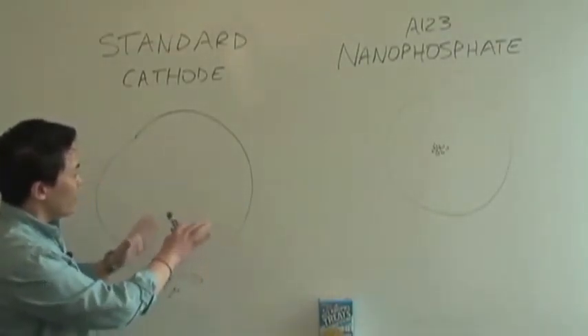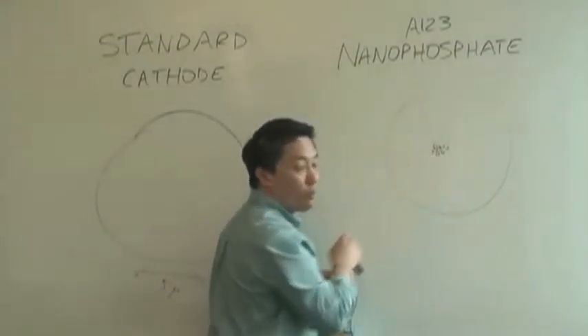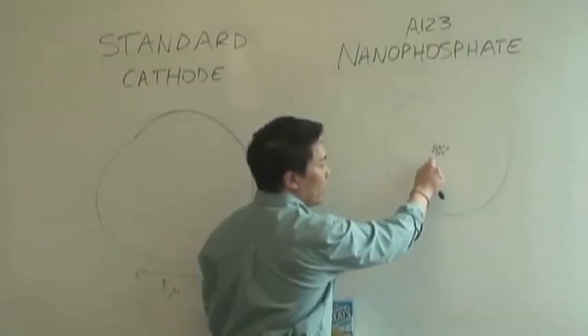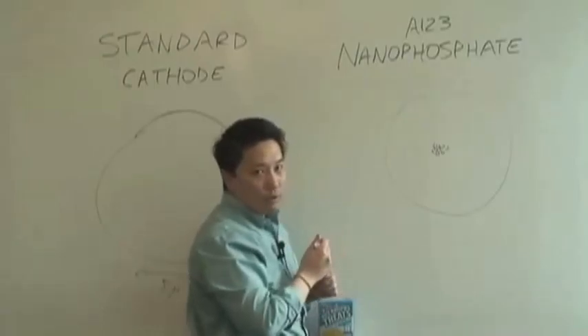Now the advantage of this structure is that the electrolytes can get in between these individual particles. And therefore, the lithium doesn't have to travel as far to completely fill or empty any individual particle.